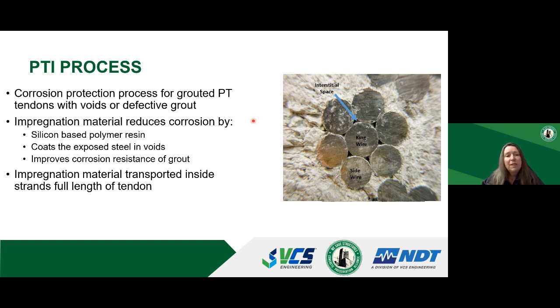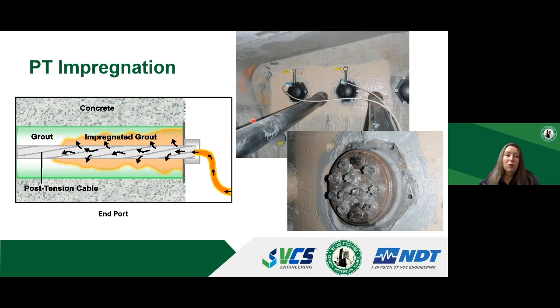During the impregnation process, a low viscosity silicon-based polymer resin is injected into the tendon. It can be injected through the anchorages or at any point along the tendon length. This material has an extremely low viscosity. It travels inside the interstitial spaces around the king wire and coats the exposed strands in an anti-corrosion coating. This material will also penetrate into the voids surrounding the strands and areas of soft grout.